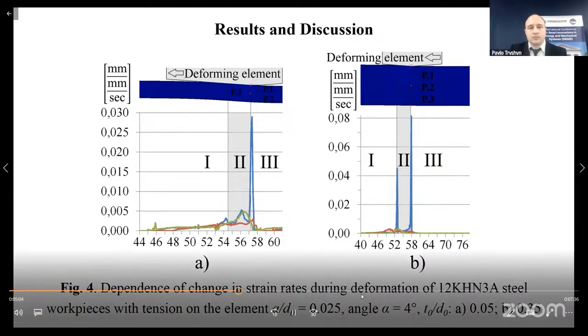With an increase in the thickness, figure 4b, the contact pressure increases and it begins to exceed the critical pressure. This affects the change in strain rates. The appearance of two zones of local plastic deformation at the beginning of the contact zone and at its end is clearly visible. In this case, the value of local plastic deformation is higher than during the deformation of thin-walled parts and reaches Xi equals 0.04 at the beginning of the contact zone and Xi equals 0.08 at the end of the contact zone.